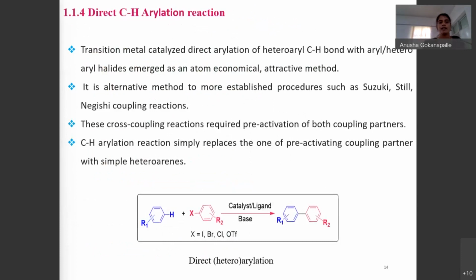Direct C-H arylation reaction. Transition metal catalyzed direct arylation of heteroaryl C-H bonds with aryl halides has emerged as an atom economical and attractive method. It is an alternative to more established procedures such as Suzuki and Stille coupling reactions, because here we are replacing the pre-activation group with simple arenes, and we can get C-C bond formation.